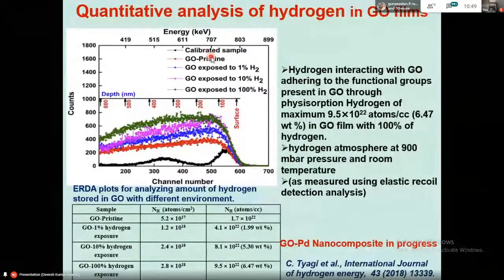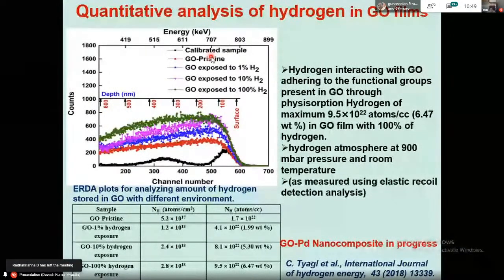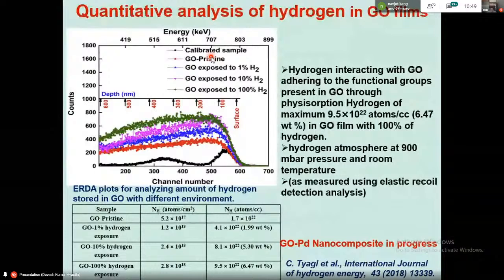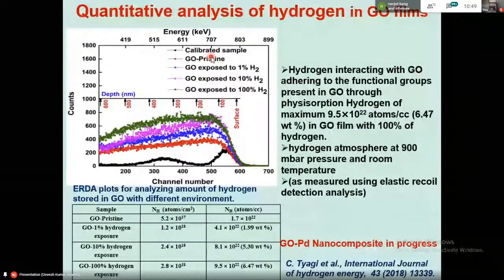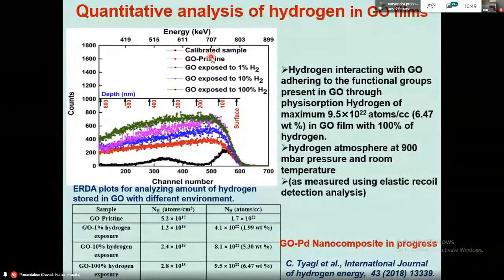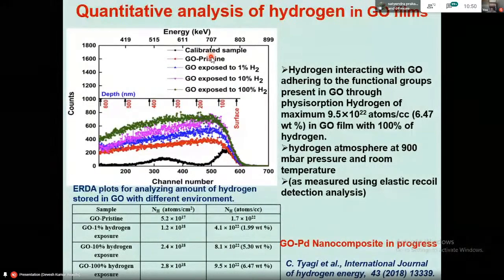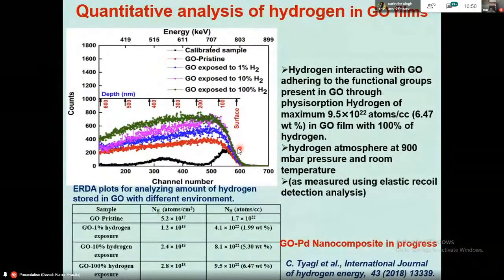And this was carried out using a technique called elastic recoil detection analysis. In this technique, the ions are bombarded on it, and the hydrogen recoil is detected in a detector. And this is a spectrum. In the pristine, that means in GO, this is the curve, the black one. So there is a very little amount of hydrogen at the surface and little inside.